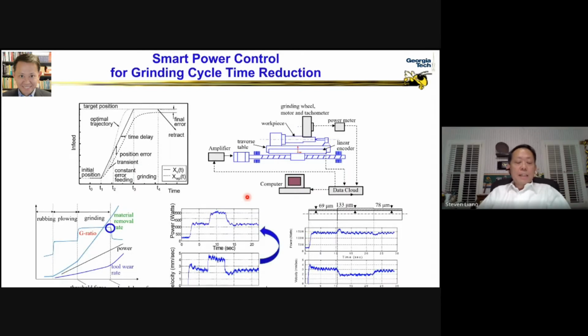And this is another example, not in the surface flat grinding process, but a cylindrical grinding process, where typically, maybe in everybody's daily experience, we typically experience error coming from transient positioning error, as well as steady state final in-feed error. So what we're trying to do is to control the grinding power at an optimal level. That would guarantee the G ratio to be maintained at a value that maximizes the material removal rate with respect to the tool wear rate. And we found that the power is quite sensitive to the velocity.